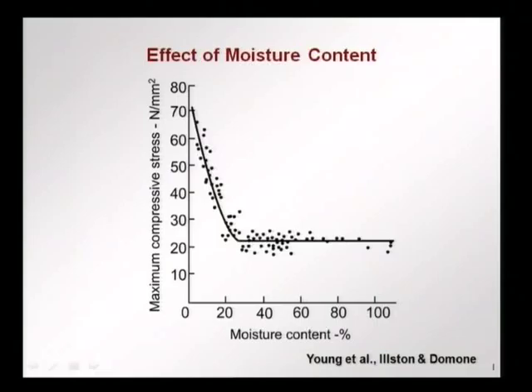So, this graph tells us what we discussed in the previous slide, where we have on the x axis the moisture content of wood, and on the y axis we have the maximum compressive stress or the compressive strength of wood. And as we remove moisture, say we have a green wood with about 100 or 120% moisture content. We start removing the water, we remove the moisture, and now we are first removing the free water. So, we remove the free water, the strength does not change much with this change of free water content.